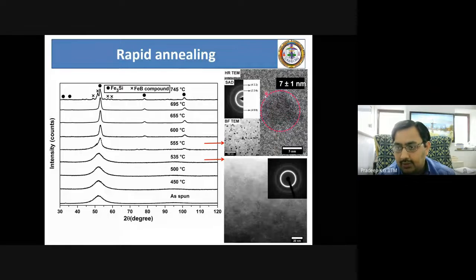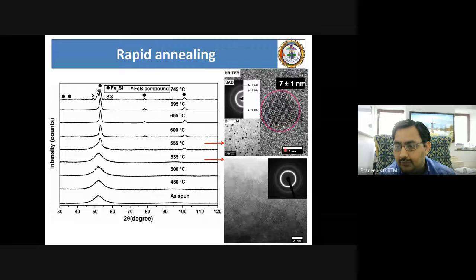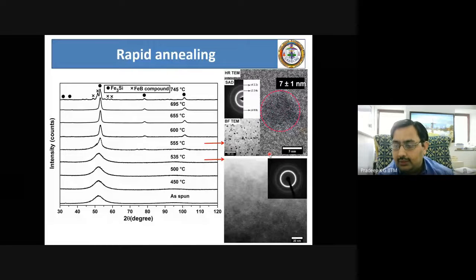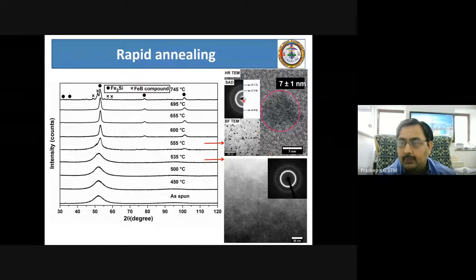That means you have some crystalline phase of 7 nanometer embedded in an amorphous matrix of whatever the leftover material is, and the diffraction pattern confirms that you have an amorphous matrix because of the halo ring pattern, and you have the spot pattern corresponding to all these nanocrystalline grains that are present inside. So this is what you can understand by looking into these microstructures.